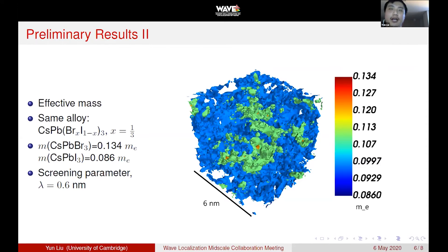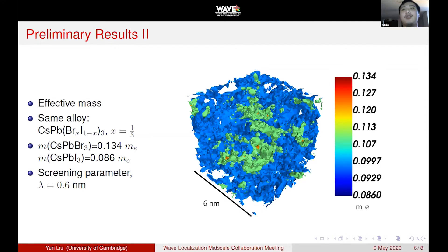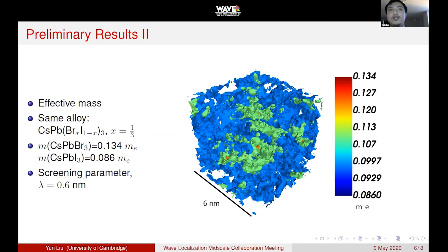There are many parameters we can vary in these systems, including the screening parameter. To generate these images, the screening parameter used is 0.6 nanometers — one lattice parameter of the cubic phase perovskite. The effective masses and band edge positions were taken from first-principles calculations such as DFT and Green's function methods from the literature. Essentially, we are building a multi-scale modeling approach: computing physical properties from high-level atomistic simulations, then feeding those values into the landscape framework as a finite element problem solvable at a larger length scale.